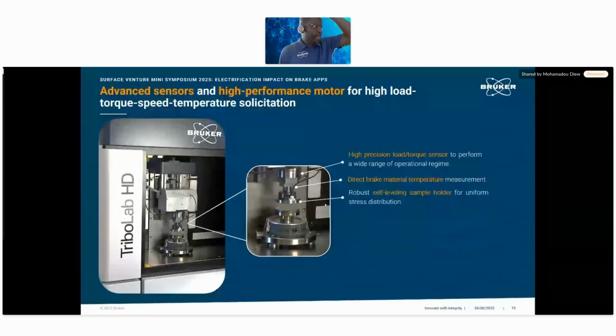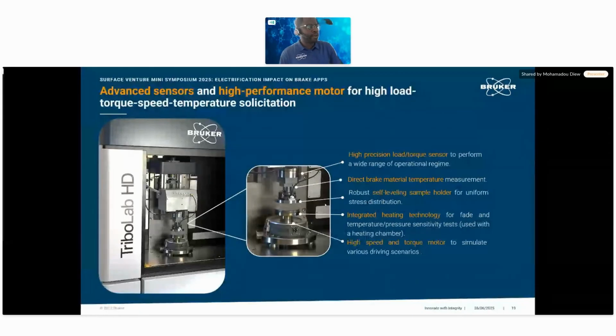I already went over this. You have different points: high speed, high torque, integrated heating on the rotary disc, and a self-leveling holder. It will be the same even on the TriboLab UMT. This makes sure that if you have two flat surfaces, they are in perfect, conformable contact. It is sometimes better to have this self-leveling to compensate for tilt that can happen, because no surface is perfect. And you can easily characterize your system with small samples. Here you can go up to 100 millimeter in size of rotor disc, and 3 coupons up to 380 square millimeter.